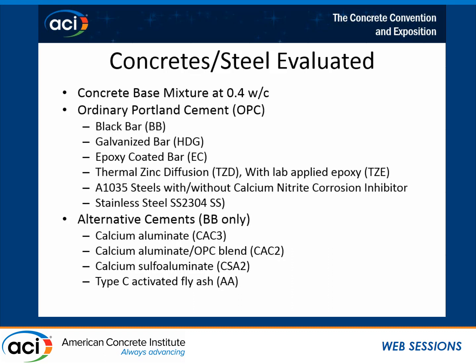For alternative cements, we only looked at black bar. We looked at calcium aluminate cement, another calcium aluminate cement that had a little bit of a cementitious blend with some normal OPC, calcium sulfoaluminate cements, and we also looked at a type C activated fly ash.